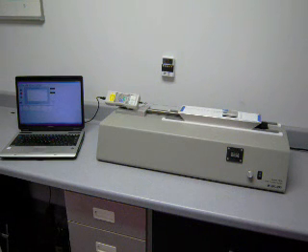Record the visual average reading during a run of approximately 130 millimeter or 5 inch while the surfaces are sliding uniformly over one another. This is the kinetic force required to sustain motion between the surfaces and is normally lower than the static force required to initiate motion. After the sled has traveled over 130 millimeter, stop the apparatus and return to the starting position.